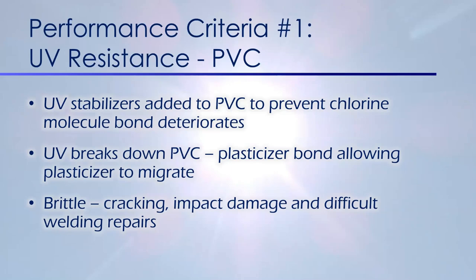So while that liquid plasticizer is there to add it to it, it doesn't stay. It migrates out of the sheet over time. That's why you see so many PVCs that are thicker. You'll see PVCs that are 60 mil, 72 mil thicker. The thicker the PVC, the longer it takes for that plasticizer to migrate out. It's not a choice of whether it's going to migrate out or not. It's just a matter of time of when that's going to happen. That's an issue with PVC.